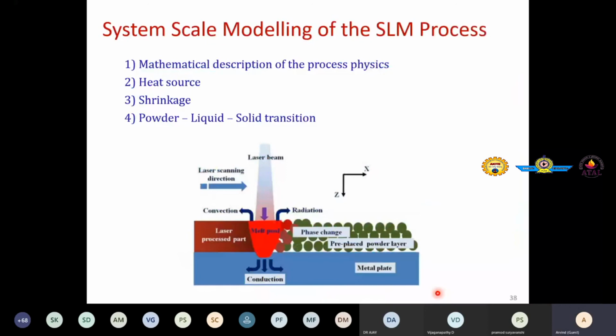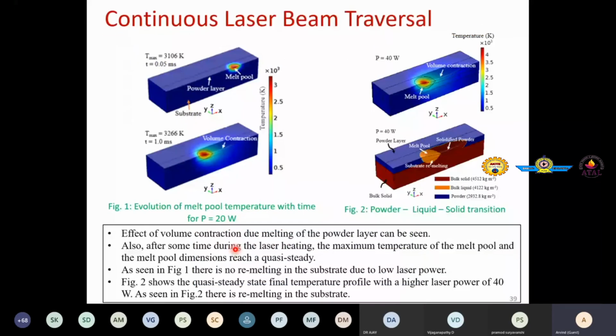To further some results on modeling, like this process modeling, we consider here a mathematical description of the process physics. The laser heat source was modeled, shrinkage was modeled, and various phase transitions from powder to liquid to solid have been modeled. The result shows, when the laser beam is scanning from right side to left side, how the thermal field is evolving and the melt pool is evolving.